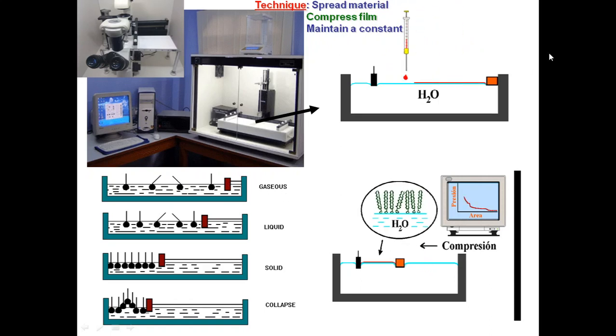Now, when some suitable amphiphilic molecules, or non-amphiphilic molecules, or some polymeric materials or nanoparticles, as a dilute solution in a volatile solvent, say chloroform, are spread gently on the water surface at the air-water interface using a microsyringe, dropwise, and sufficient time is allowed to evaporate the volatile solvent, then the amphiphilic molecules lie haphazardly on the water surface, as shown in this figure. This state may be compared to the gaseous phase, because the molecules are away from each other and there is less interaction between the molecules.